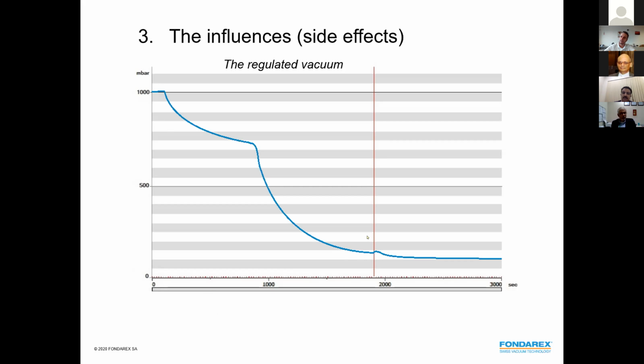And when we are filling the part in this area, we still have a very good vacuum level. And therefore, you get a better quality casting, because we were able to fill the cavity with the plunger movement. As we heard before, the Bühler machine, Frech, and Idra Press have a programmed shot, and you can put in some acceleration in the first phase. So with the characteristics you give to the metal flow through the first phase velocities and acceleration, we are able to regulate the vacuum exactly so that the metal flow gets close to perfect in the first phase.